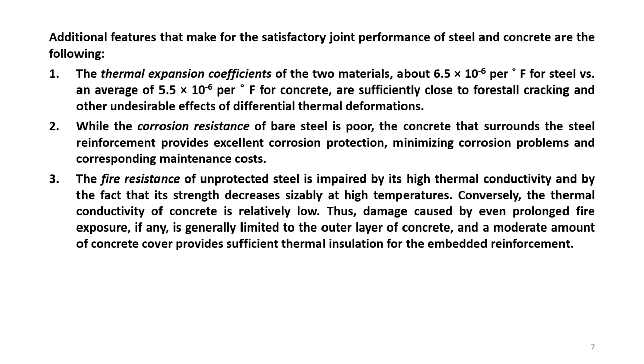One major thing is the thermal expansion coefficients. The thermal expansion coefficient of steel is 6.5 × 10⁻⁶ per degree Fahrenheit, and for concrete it is very close — 5.5 × 10⁻⁶ per degree Fahrenheit. This similarity means the two materials will act simultaneously and combinedly. When heated, the expansion of one will not be far from the expansion of the other, so they remain altogether intact.